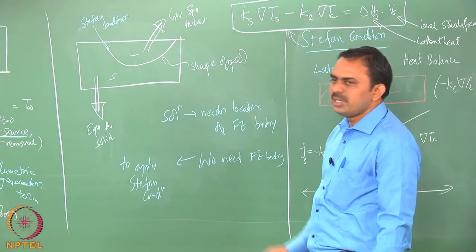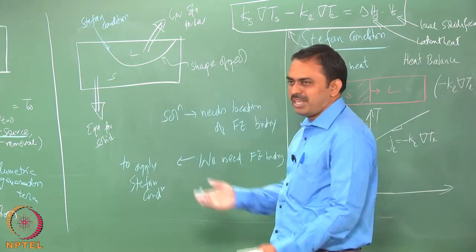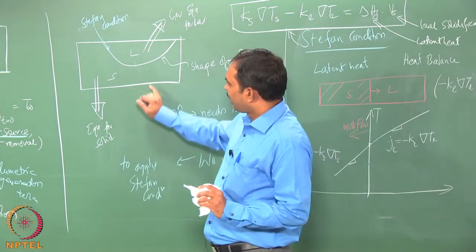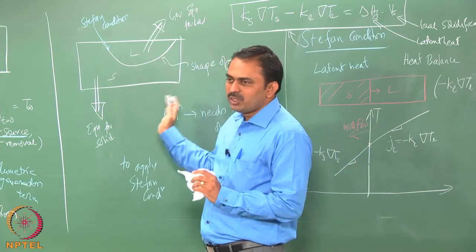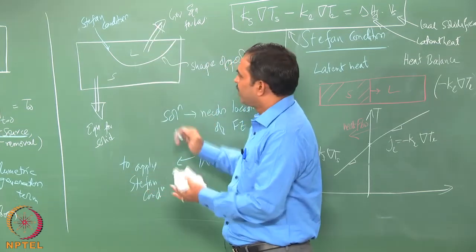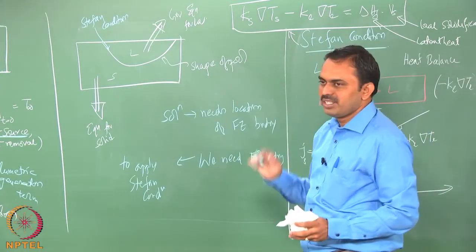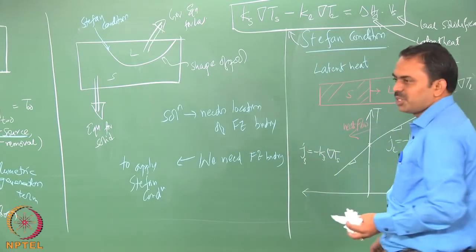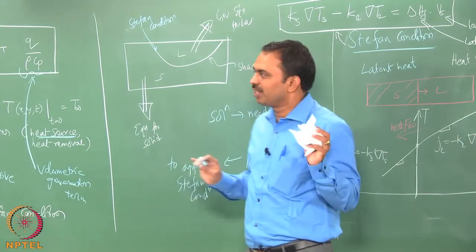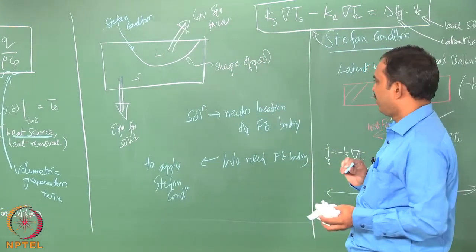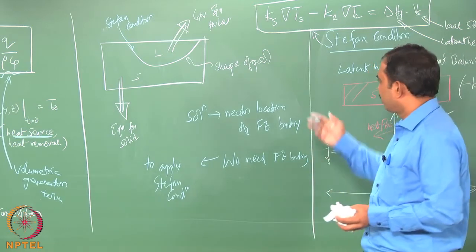There are ways to go about this. Normally you approximate the rough shape of the pool, solve the thermal field in both domains separately using FEM or control volume methods, then iterate by changing the shape until there is total thermal balance — where heat supplied by the heat source equals heat lost to the environment to sustain the liquid pool. However, it is also very convenient to have a single equation applicable to both domains simultaneously, and that can be developed by introducing one additional variable.